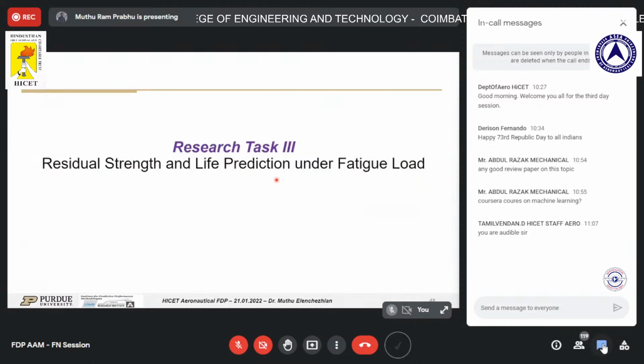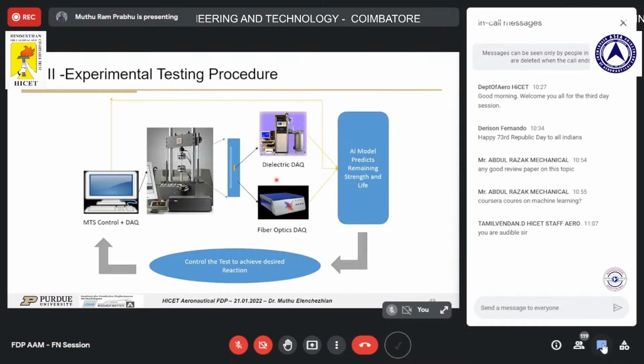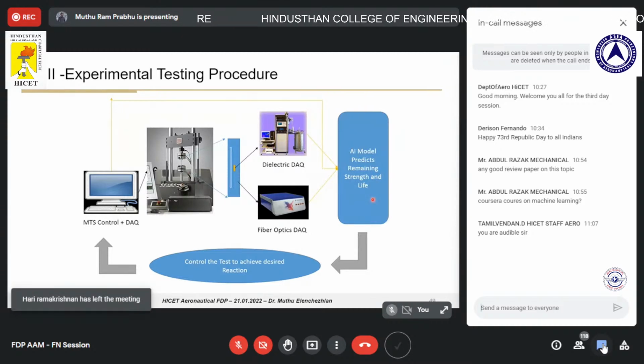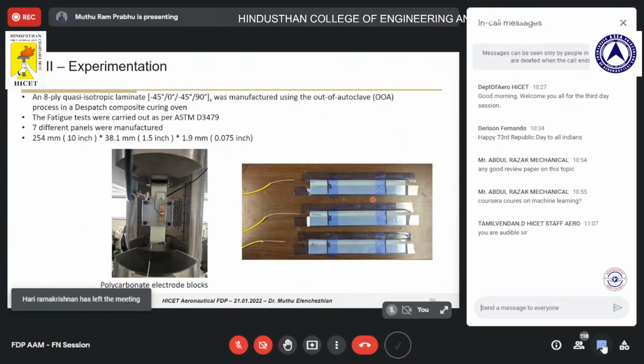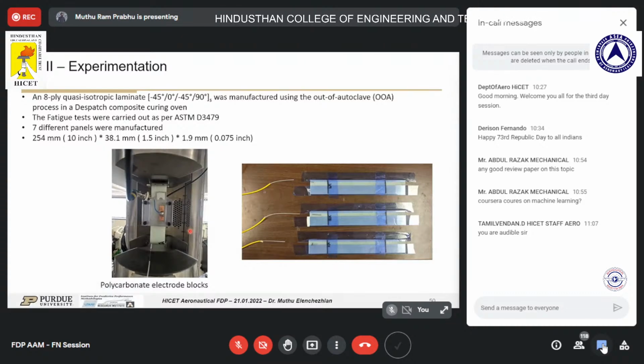And the final task which I performed was to do it under fatigue load, that is, under cyclic loading conditions. So in this case, we did mechanical testing under fatigue loading conditions for the samples. And in this, we collected the dielectric data, and simultaneously, we also collected the fiber optic strain data and developed the AI model, which can predict the strength and life of the material. So a similar kind of test was done.